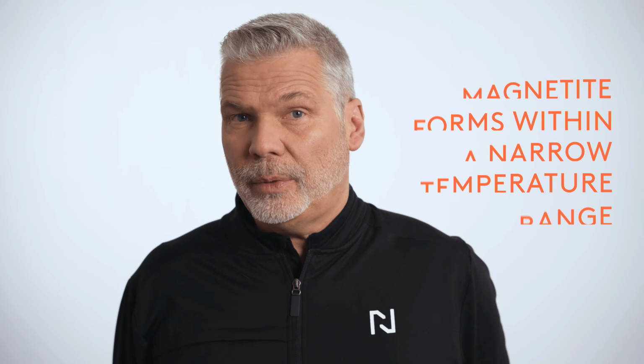At the end of this stage, the process adjusts to the correct temperature for post-oxidation. Magnetite is produced in a very narrow range of temperatures and a specific amount of oxidants. Once the components are at the desired temperature, we introduce an oxygen carrier. It can be water, water vapor, or nitrous oxide.